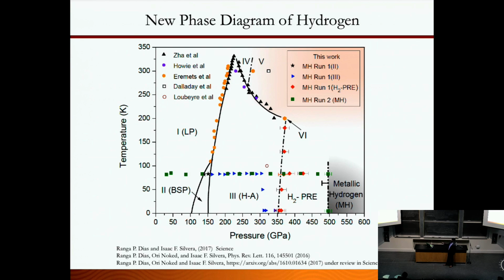Then these are all our measurements. You can see the new phase line here, and the new phase we observe has also been observed by the other group, the Eremets group of Max Planck. He observed the same thing. He was squeezing at room temperature and coming down in temperature, so he was seeing the exact same thing we have observed right here. So you can match the phase line right here. And if you go up in more pressure, you get this metallic hydrogen.